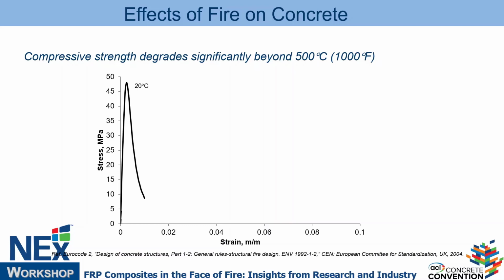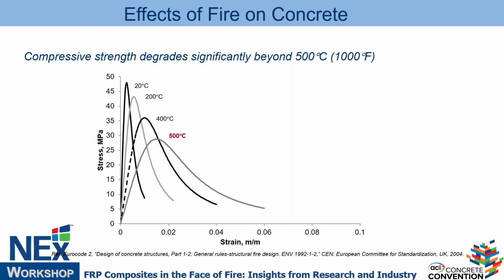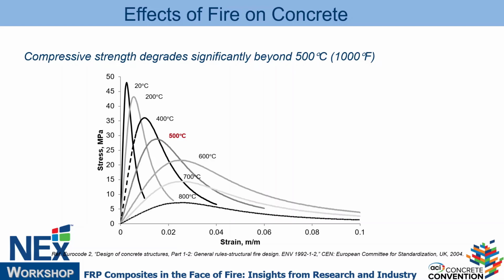At 20 degrees C, there's a certain behavior. Oh, sorry, this is the concrete. We start with the compressive strength. You get to the peak, right? This is what we call f'c, and then after that, you get failure. And as the temperature rises, the compressive strengths start falling apart, right? You lose strength, you lose stiffness of the material, right?